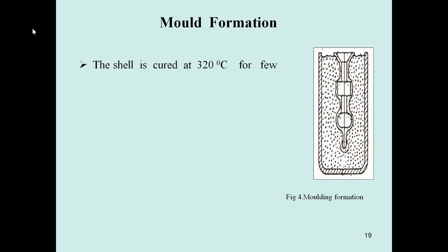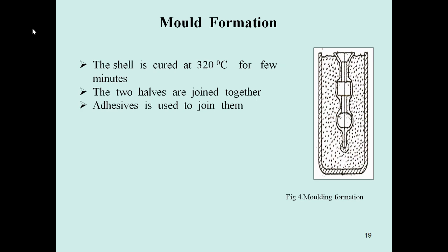The shell is further hardened by a final curing for a few minutes at about 320 degrees centigrade. Okay, next, the two halves are joined together by adhesive to form the mold.